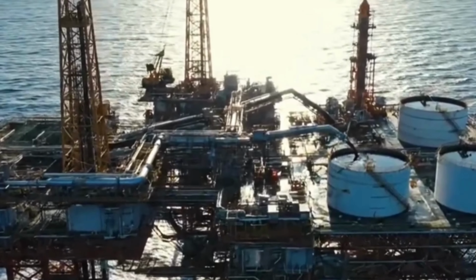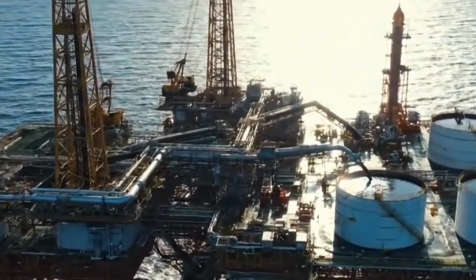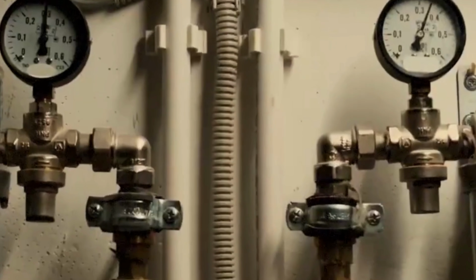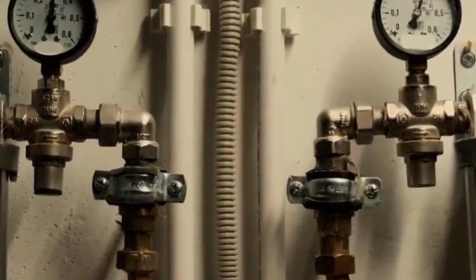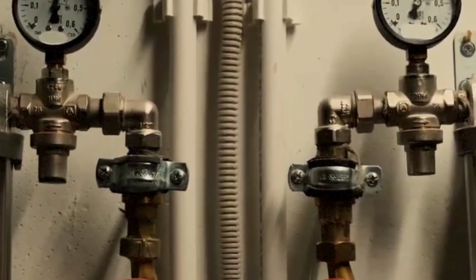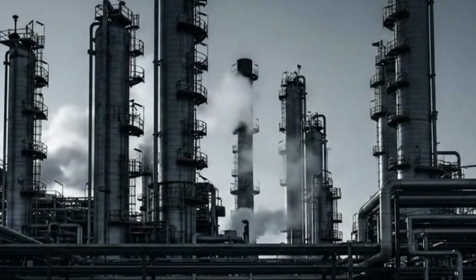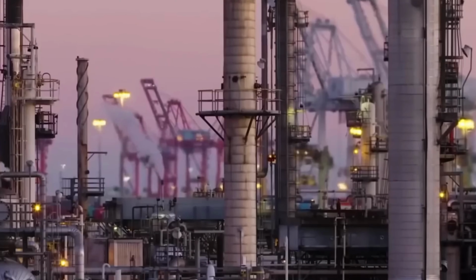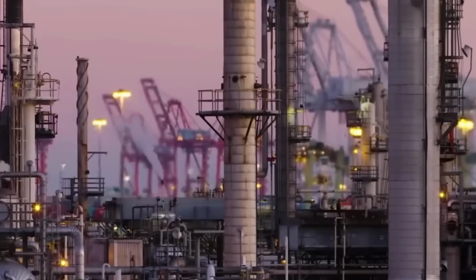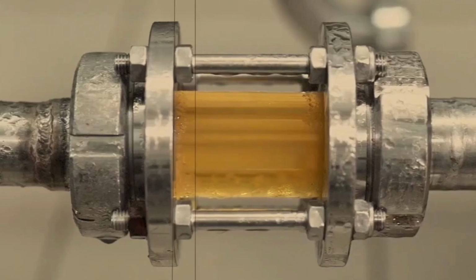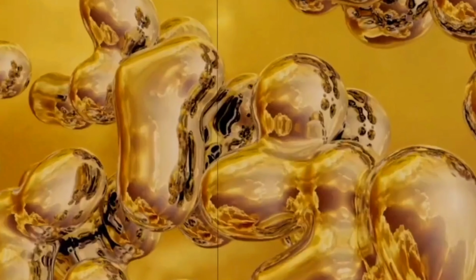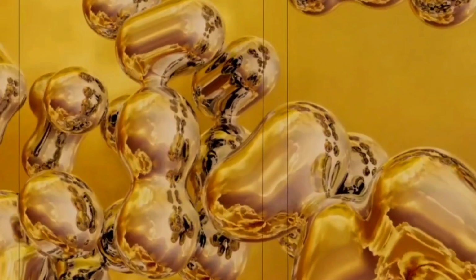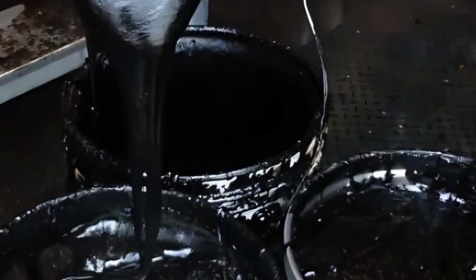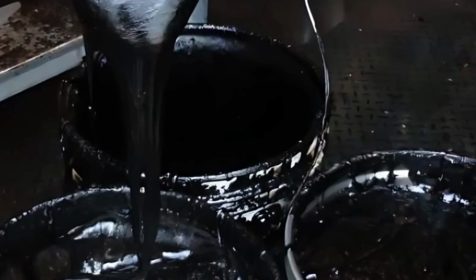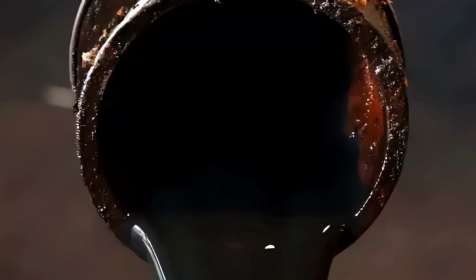The first step is atmospheric distillation, the refinery's primary separation process. Crude oil is heated in large furnaces to around 350 to 400 degrees Celsius, and then fed into a tall distillation tower. Inside the tower, hot vapor rises and cools as it climbs. Lighter fractions condense at higher levels, while heavier fractions condense lower down. This creates streams like gasoline, kerosene, diesel, and gas oil, each pulled off at different points. What remains at the bottom is the thickest, heaviest residue, the starting point for bitumen production.